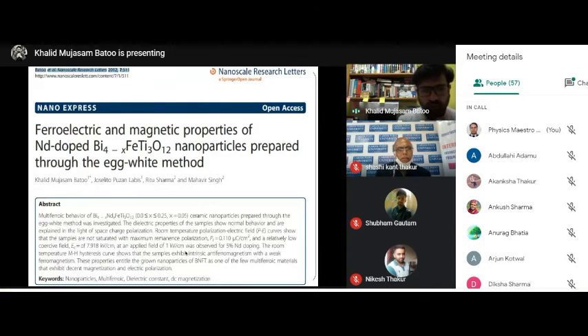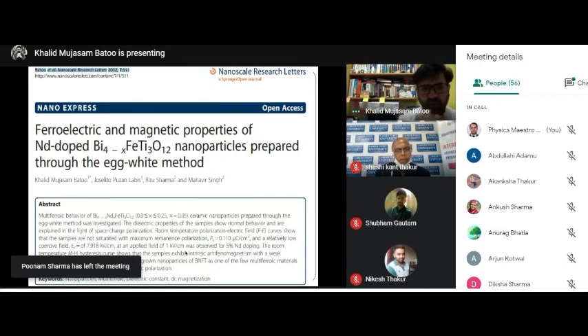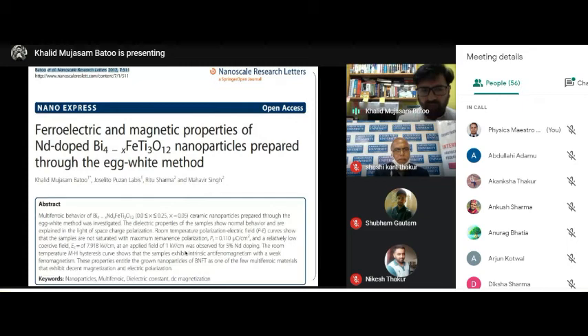Let me go to the work which we have done in the case of ferroelectric materials. We started not with barium titanate, we started with bismuth. We doped bismuth with Nd, a very good material. If you dope barium titanate or bismuth titanate or any other material with it, it actually increases the polarization, helping increase the ferroelectric character of a material.